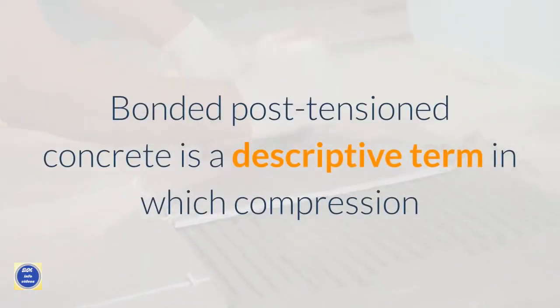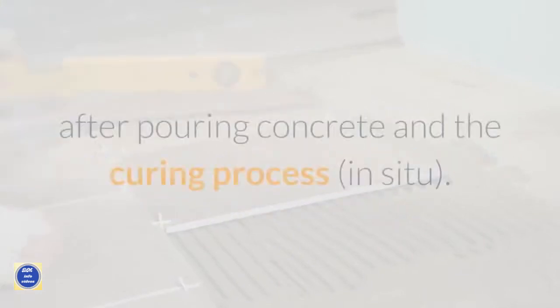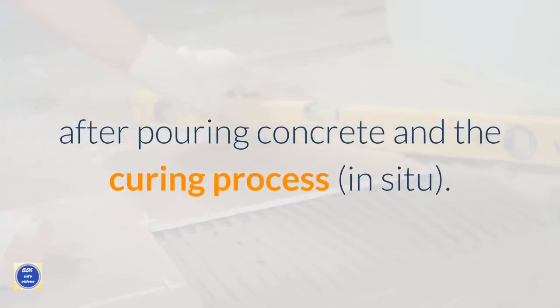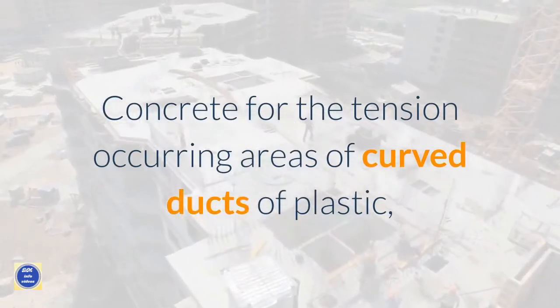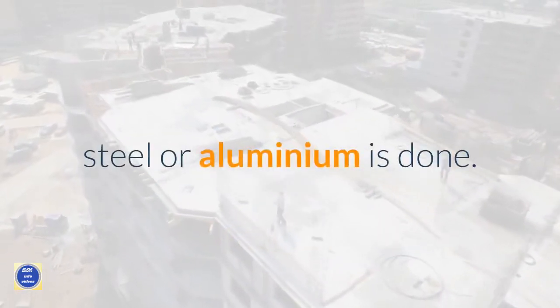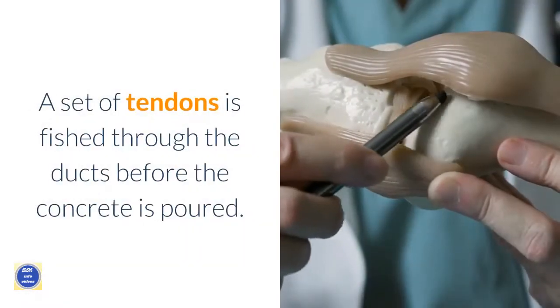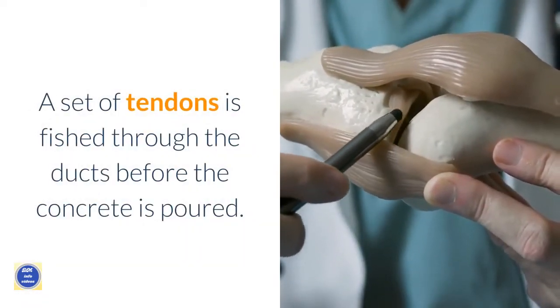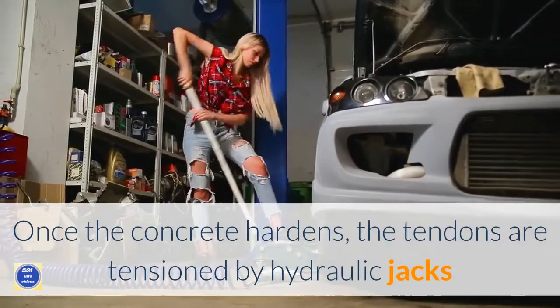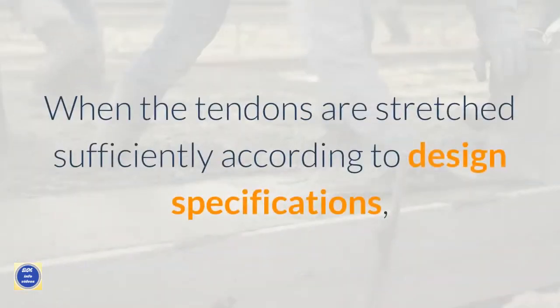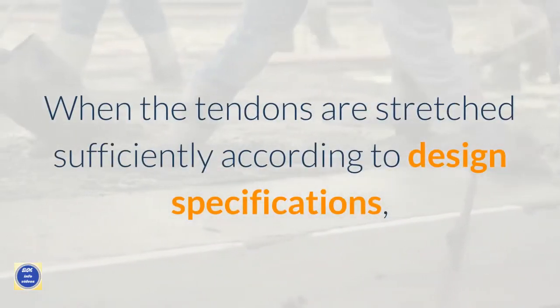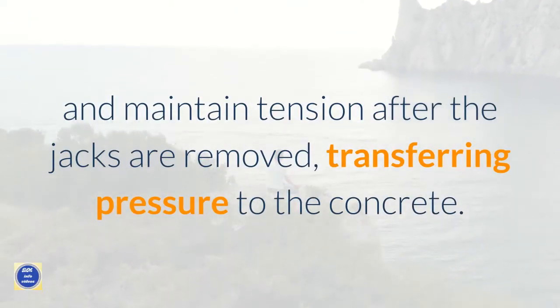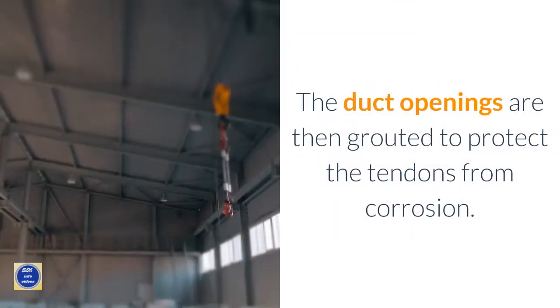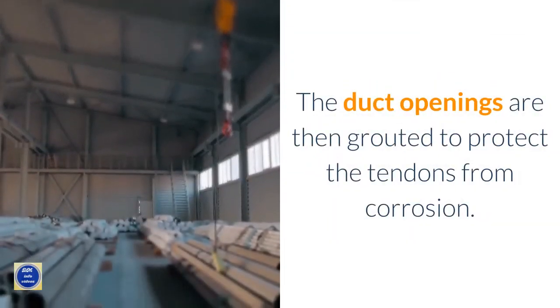Bonded post-tensioned concrete is a descriptive term in which compression is applied after pouring concrete and the curing process, in situ. Curved ducts of plastic, steel or aluminium are placed in the concrete for the tension-occurring areas. A set of tendons is fished through the ducts before the concrete is poured. Once the concrete hardens, the tendons are tensioned by hydraulic jacks that react against the concrete member. When the tendons are stretched sufficiently according to design specifications, they are wedged in position and maintain tension after the jacks are removed, transferring pressure to the concrete. The duct openings are then grouted to protect the tendons from corrosion.